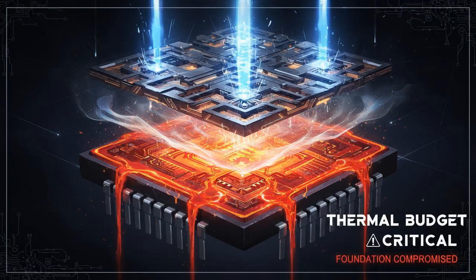If monolithic 3D is so revolutionary, why don't we have it yet? The answer is heat. Making high-performance transistors for the bottom layer requires extreme heat, over 1000 degrees Celsius, to activate the dopants and crystallize the silicon. You build the bottom layer at 1000 degrees, and it is robust. Then you add copper wires to connect the bottom layer. Copper melts at 1085 degrees, but more importantly, it starts migrating and destroying transistors at anything above 400 degrees. If you then try to build the top layer using the standard 1000-degree process, you will melt the copper wires and destroy the transistors in the bottom layer. This is the thermal budget challenge. The top floor must be built at temperatures below 400 to 500 degrees, or the foundation will collapse.